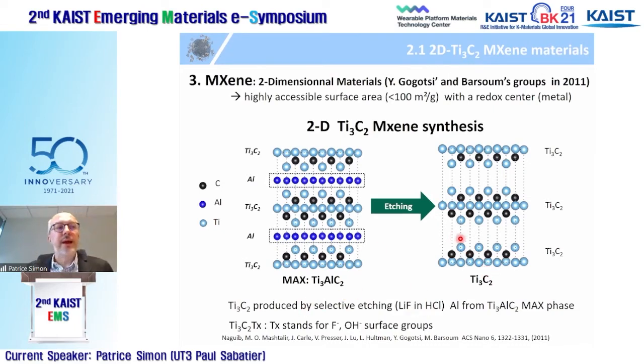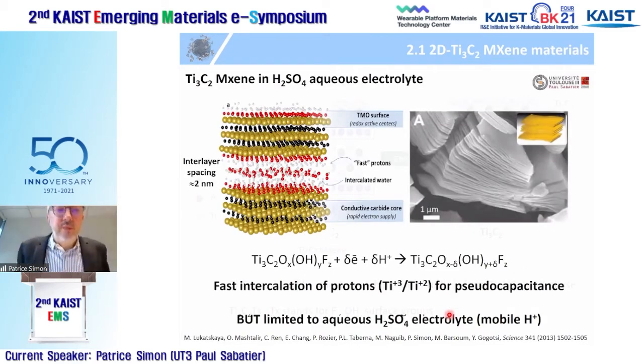Obviously, because of the etching preparation, your Ti3C2 MXene contains surface groups. And these surface groups are driven by the etching electrolyte. Here, most of the MXenes contain fluorine and OH minus groups because of the etching in fluorine-containing aqueous electrolyte. As you mentioned before, the beauty of these MXenes is that they have super high electrical conductivity, and they have a transition metal, titanium in this case, and you can store energy by changing the redox state of the titanium.